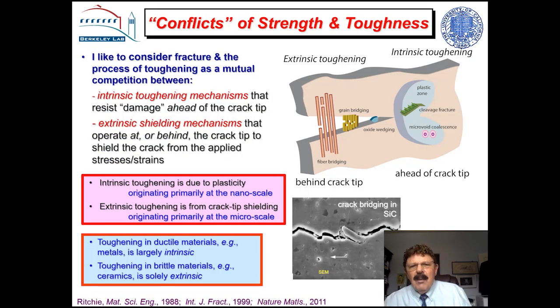Now, why is this? Well, toughness is often a mutual competition itself. Toughness is resistance to damage in the materials, and that's what I call intrinsic toughening. This takes place generally ahead of the crack tip. Damage is in the form of breaking particles, cracking the matrix, causing decohesion, and it's generally resisted by plastic deformation or plasticity or whatever form of inelastic deformation you have. This is the main source of toughness in metals, and it occurs ahead of the crack tip. But you can't use that very readily for ceramics.